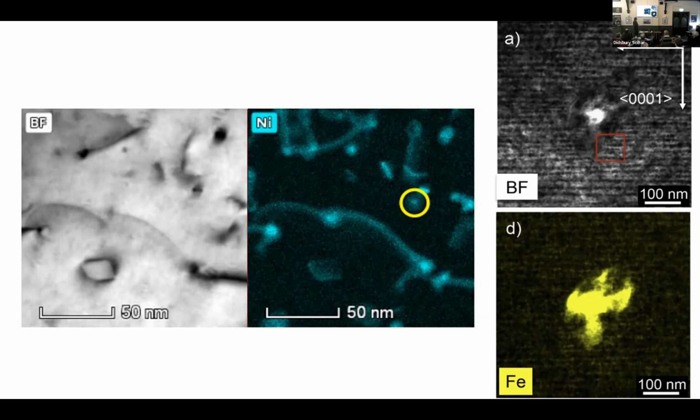And they move in all sorts of complicated ways. Sometimes they like to clump together and form new, even more obstacles. Or sometimes we actually wanted them to clump together in the first place, and then the radiation dissolves them. You can't win. You can see this was supposed to be round. This would have been round basically when it went in, and now it's all dissolved out.